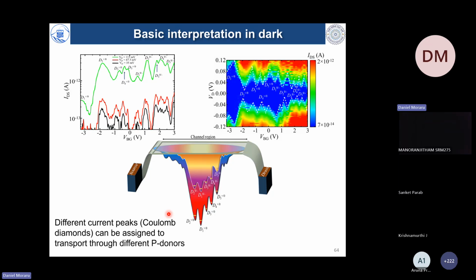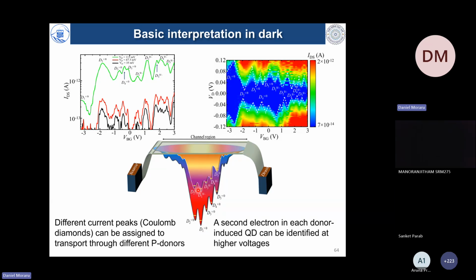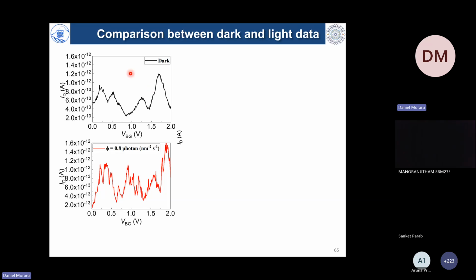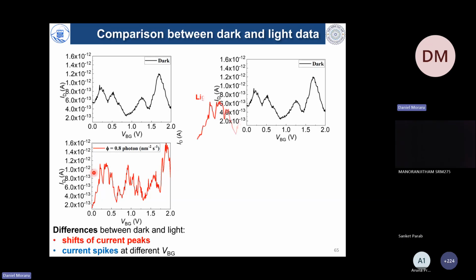It's very important to understand that transport occurs through different phosphorus donors, and each of them can be a path of current. Also, a second electron can be added into each quantum dot because we have deeper states. Now, in dark, we observed this kind of IV characteristics. Under light, however, with very low incidence of photons, we start to observe noise and also a shift of these IV characteristics. For better understanding, let me stretch these characteristics. And now you can see a better match between the dark and the light characteristics.